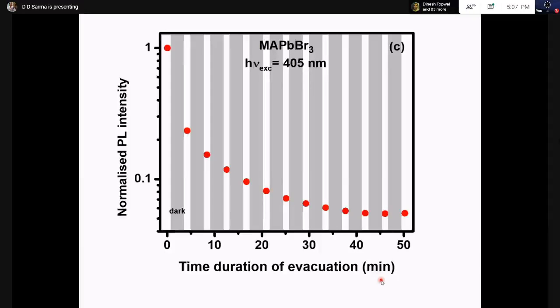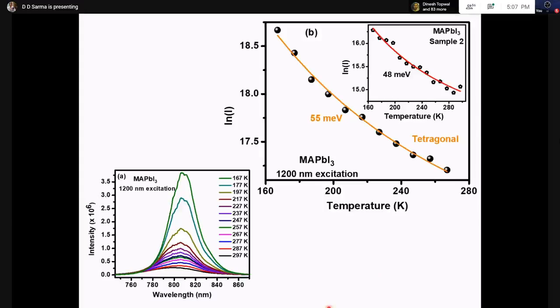And that is how we did the experiment. And you can then do the temperature variation. It's MAPbI3, a two-photon absorption induced emission experiment. You can see the excitation is at 1200 nanometer, which is a very long wavelength, lower than the band gap of the material.